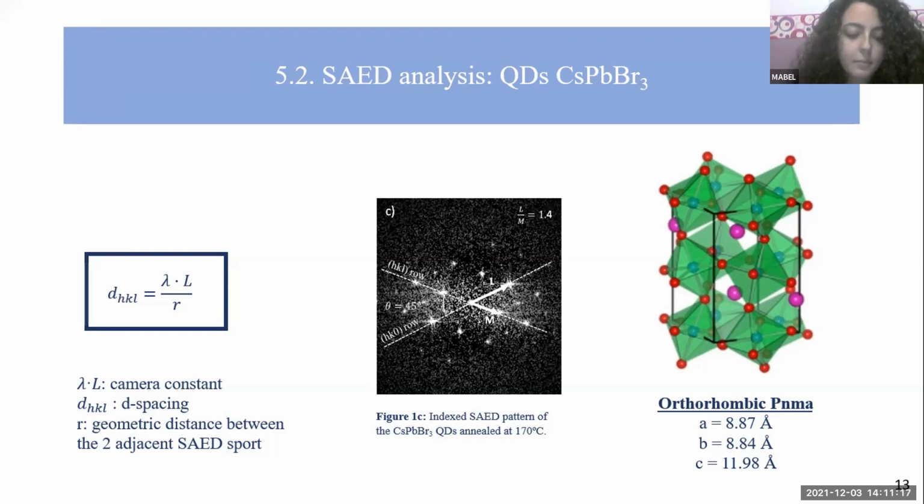On the other hand, in SAED patterns, each diffraction spot or reciprocal lattice point represents a set of equally spaced real lattice planes. Thus, measuring the angle between the HK0 and HKL Laue lines, represented by dashed lines in Figure 1C, equals the angle between the corresponding real lattice planes.